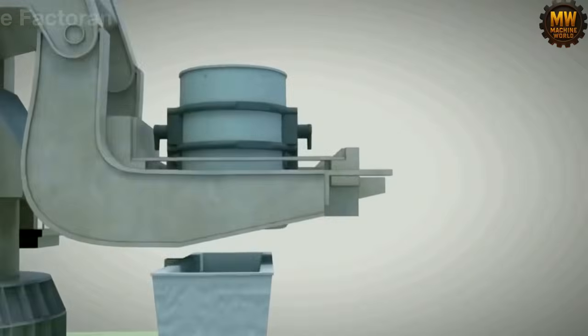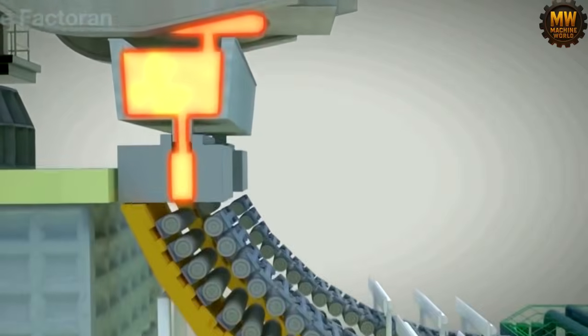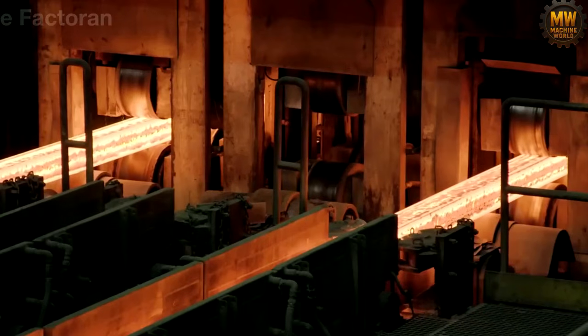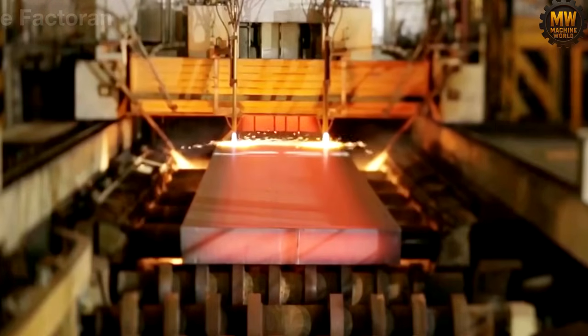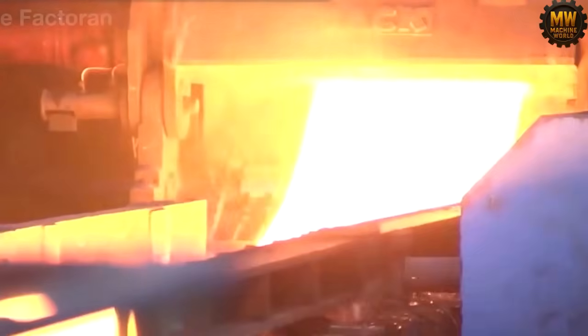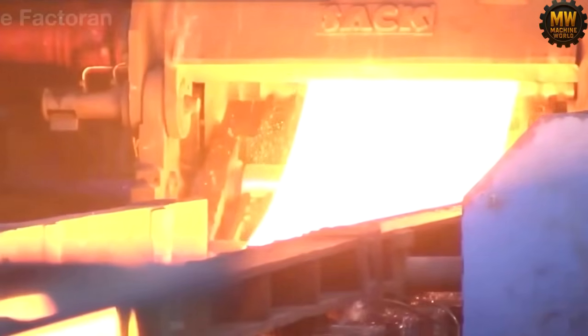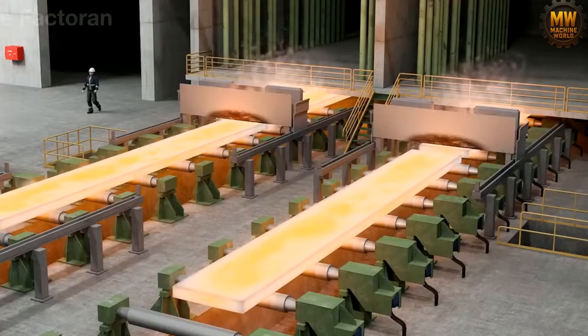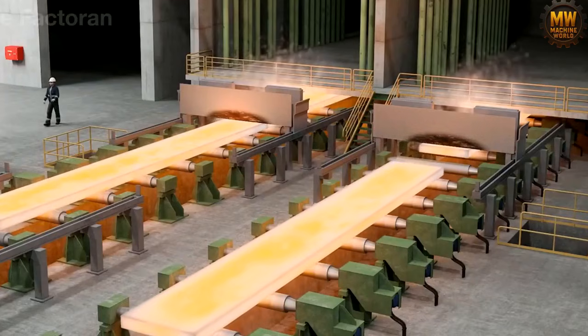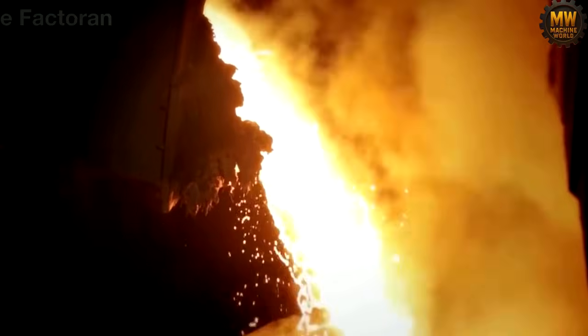A guided tapping system channels the relentless flow directly into water-cooled casting molds. Here, a physical paradox unfolds. As the incandescent metal hits the chilled walls, the outer layer freezes instantly. A rigid shell forms. Inside, the core remains pure churning liquid. This fragile structure cannot stop.